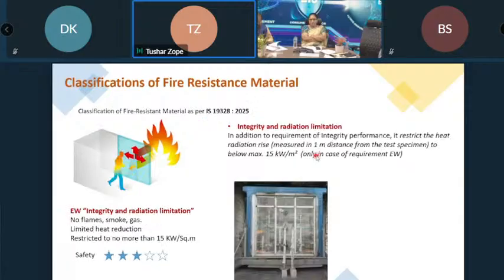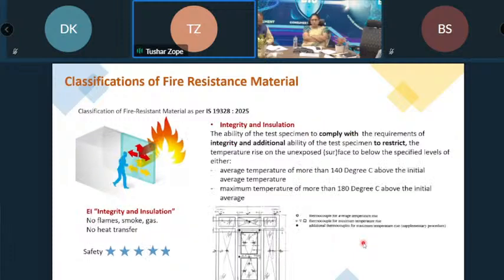Now in the EW category, we put a thermal radiometer at a distance of 1 meter from the unexposed surface of the glass, where we measure the thermal radiation. As per the standard, the thermal radiation has to be below 15 kilowatt per square meter. In the EI category, we put thermocouples on the surface of the door, partition and glass. The average temperature should not cross 140 degrees Celsius plus the ambient temperature, or the maximum temperature should not cross 180 degrees Celsius plus the ambient temperature.